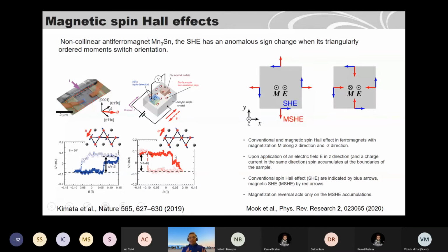Okay, so that was the basic spin Hall effect. But recently, going forward, I can show you that in 2019, people discovered the magnetic spin Hall effect. So magnetic spin Hall effect means what? It should be dependent on the magnetic field in your material. And that was discovered in a non-collinear antiferromagnet, Mn3Sn. So it's a new material. It's an antiferromagnet. Antiferromagnet means the spins should cancel out, but it's a non-collinear antiferromagnet.